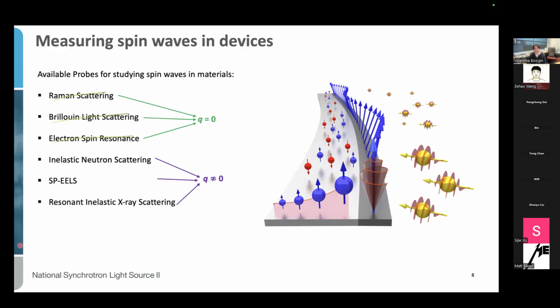So now for energy dispersed information about magnons in material, we are left with a second group here of techniques. But now, as in this talk, we are interested in devices that normally involve small amount of material, and most of the time we need to deal with the presence of electrodes. We basically rule out inelastic neutron scattering because of the volume involved, and spin polarized EELS because it's a very surface sensitive technique. So this leaves us with an open option that is resonant inelastic X-ray scattering.